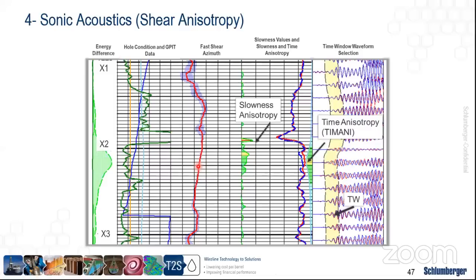And in drilling-induced fractures, or typically when we have anisotropy, we need to start fracking the well in the direction where we have the magnitude of the fast direction. So in order to start fracking the well, where we create a permeable pathway into the formation, we need to know the direction of the stresses, which has already been identified, and also the azimuth of this fast shear slowness. Typically, the slow shear azimuth would be 90 degrees from this, because we're measuring two components, the X and Y, that are 90 degrees apart.